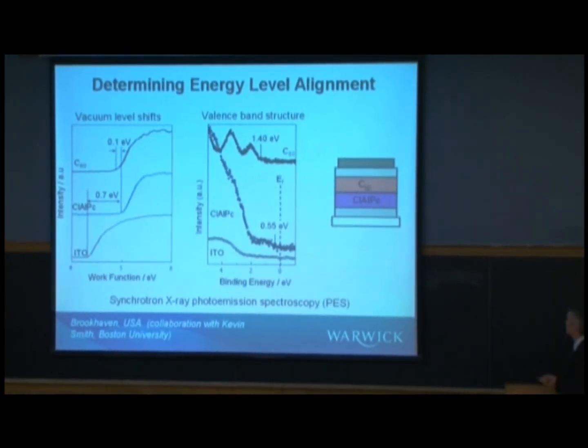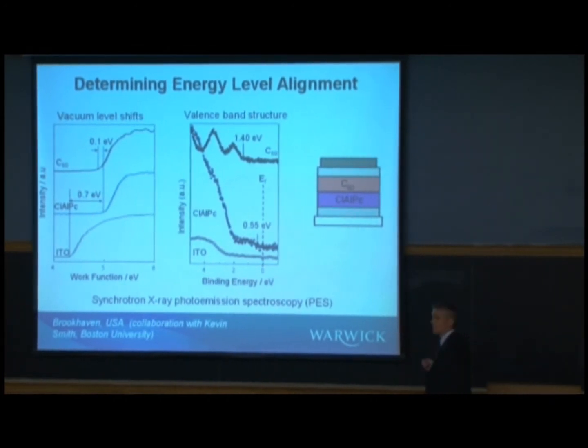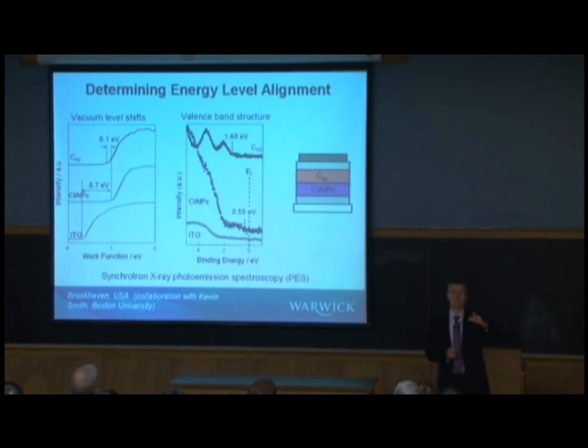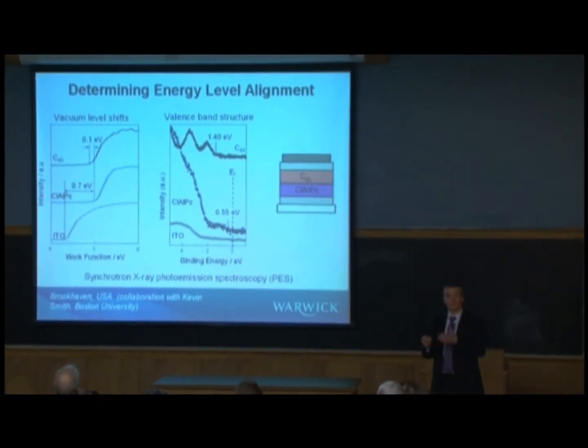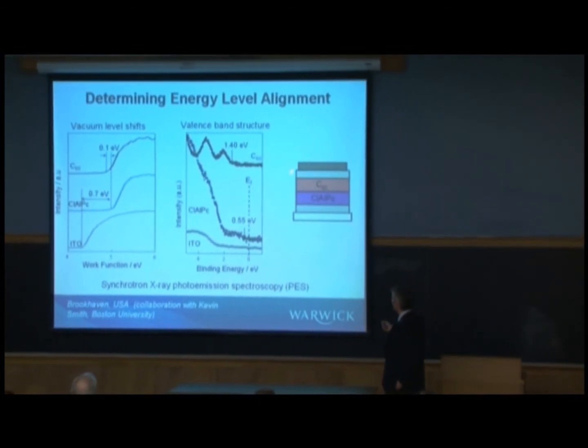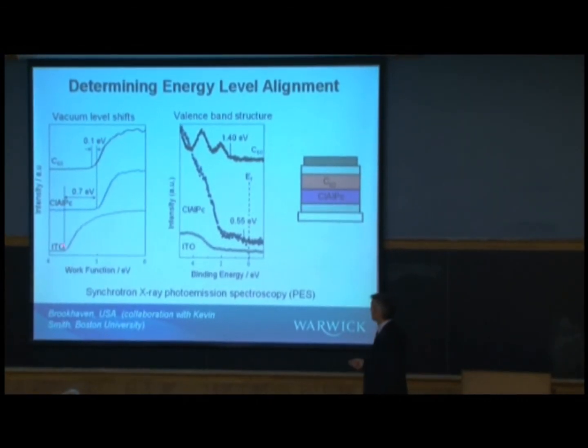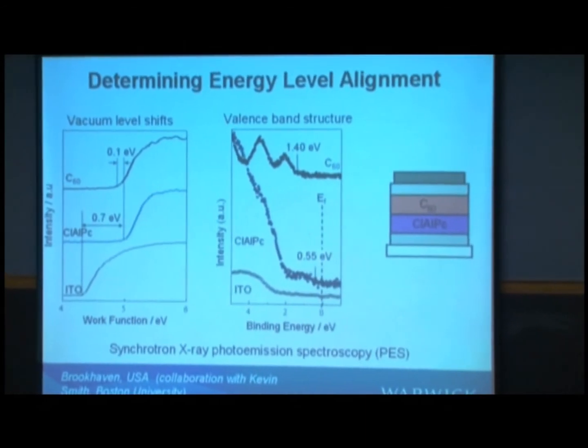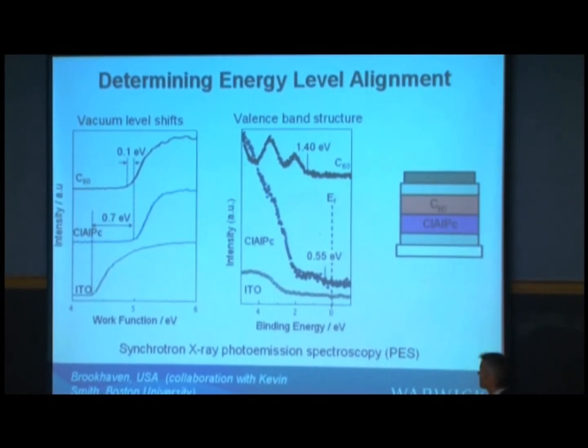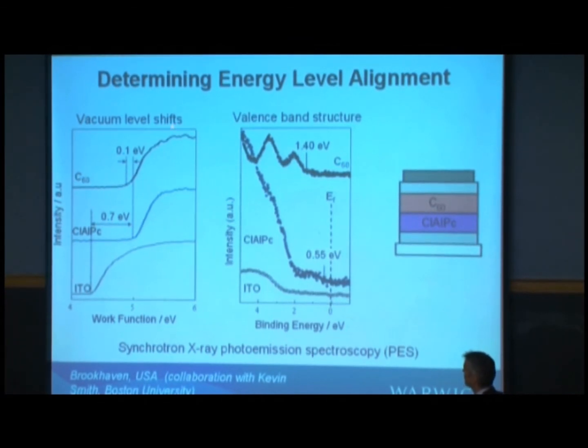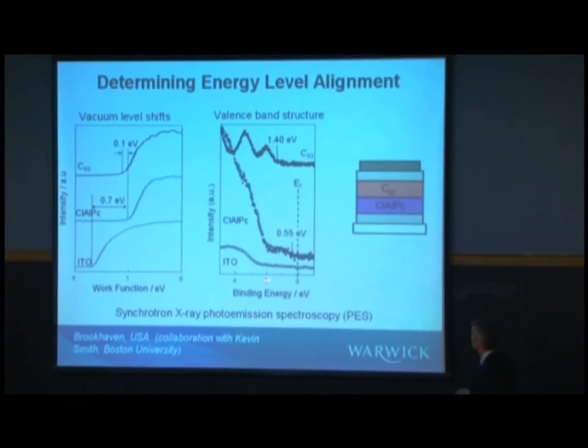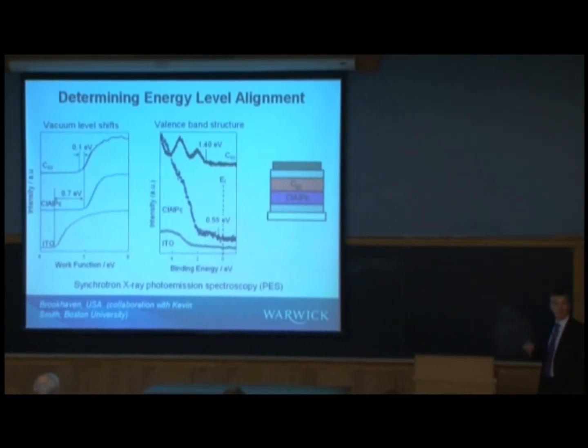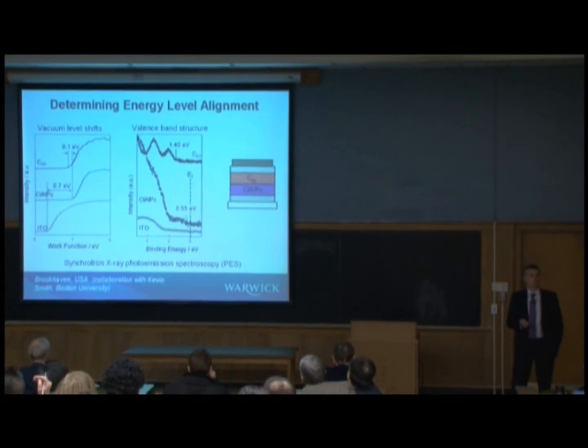This is some work done two or three years ago. As I said, the beauty of small molecules is you layer the materials in your evaporation process, so you can do measurements using techniques such as photoemission on your device structure as it evolves. These are measurements for ITO, chloroaluminium phthalocyanine, and the fullerene C60. The chloroaluminium phthalocyanine is the donor, and C60 is the acceptor. These were synchrotron measurements done at Brookhaven, but you can do lab experiments as well, looking at the vacuum level shifts as you build up your device, but also at the valence band structure and the onset of the HOMO levels, which you need in order to understand the energetics.